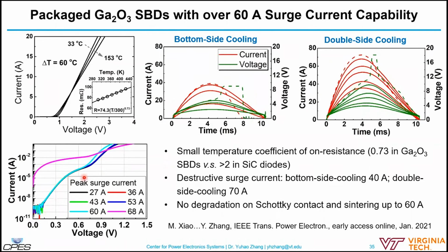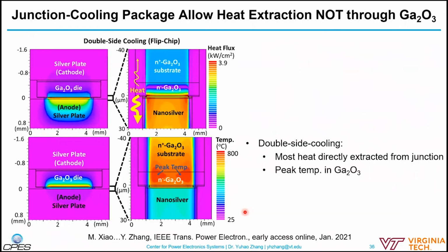And from here you can see there is no degradation of the Schottky contact and the packaging up to the surge current of 60 amps. Okay, and here shows the simulation result that illustrates why this double side cooling allows the higher surge current. So here is the simulated heat flux in this double side cooled structure. This is a flip chip structure, so on the bottom is the anode. From the heat flux, this is the zoomed-in region of the entire structure.